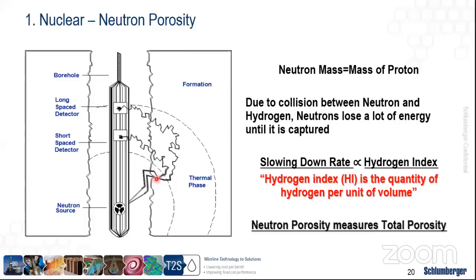So the slowing down rate is proportional to the hydrogen index. As I said before, we start at very high energy, and the rate of slowing down, how much time it takes to slow down the neutron to reach the thermal state, is proportional to the hydrogen index. So hydrogen index is a quantity which represents how much hydrogen we have per unit volume. The more hydrogen we have, the higher the slowing down rate of the neutron would be. The less hydrogen we have in the borehole, the slowing down rate would be very, very slow compared to high hydrogen index.